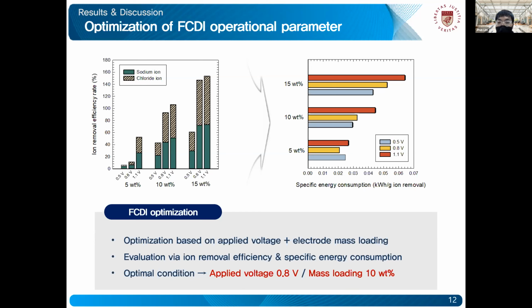So that's why, taking a look at the right figure that shows the specific energy consumption, we can see that increasing the mass loading and also increasing the applied voltage increase the energy. So comparing these two values, we found that the optimal condition was the applied voltage of 0.8 volts and a mass loading of 10 weight percentage.